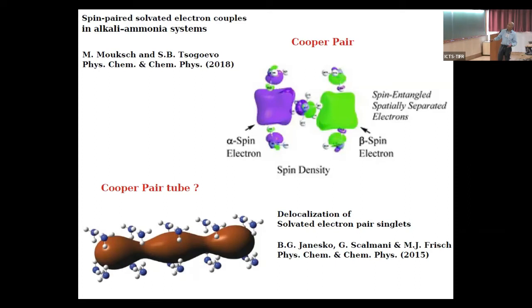So if you do an experiment, or a theoretical, detailed, sophisticated calculation, what you find is that trapped electrons form a spin singlet pair. And then if you do an even more detailed calculation, what you find is they create their own way and form tubes in which these Cooper pairs delocalize. So from the theory point of view, electrons are paired, they form very tight singlets. There is also the possibility of delocalization. So nothing prevents it from becoming a superconductor. But however, there is a frustration, the medium doesn't cooperate. So lots of problems are there. So this is still an active field in some corner.